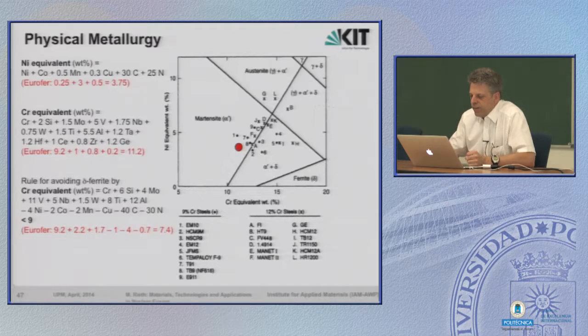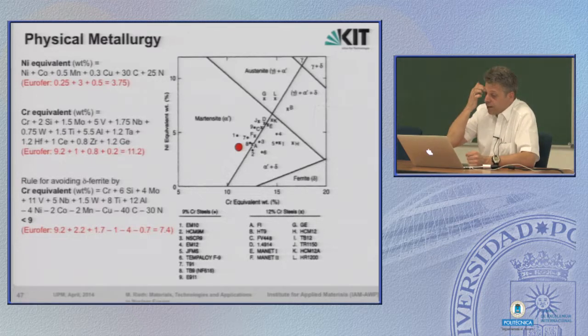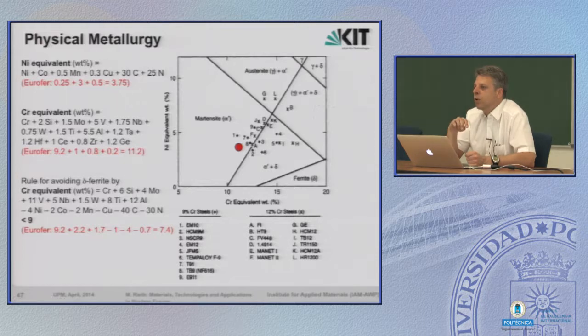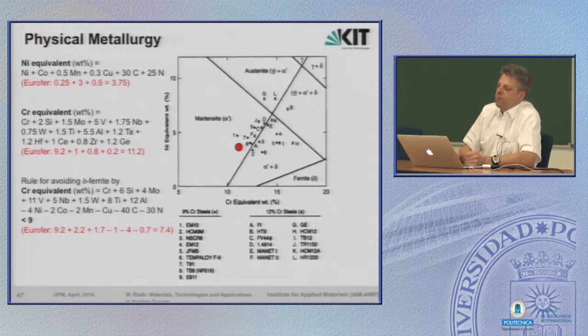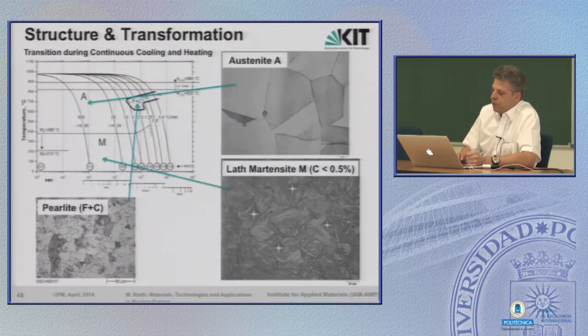For producing these 9% chromium steels, the typical classical physical metallurgy has been used. I will only give an overview. All these dots here are a variety of different 9% chromium steels and sometimes 12% chromium steels. Eurofer, as I have already shown, is here, a typical martensitic steel. And there are some rules of how to produce these steels. For example, nickel equivalent is 3.7. The chromium equivalent, that's the other type of element, is around 11. There is also a rule to avoid delta ferrite formation. This is an important topic when it comes to joining, to welding. That's part of the following lecture. This has all been considered for the development of Eurofer.